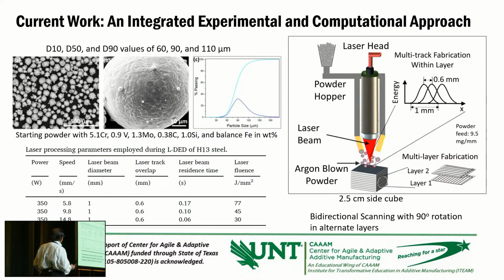There are much more complex strategies that can also be used. You can use bidirectional scanning in one layer, that is going in this direction, coming back in this direction, going in this direction, coming back in the other direction. So a bidirectional strategy can be used in one layer, and then do the same thing in a 90-degree rotation, another bidirectional scanning, and that way you can start breaking the grain growth across the layers and get much better equiaxed grains and so on. So there are a lot of ways you can control the grain structure, but in our experiment, we did only a 90-degree orthogonal rotation in a uniaxial scanning direction, to understand the process.